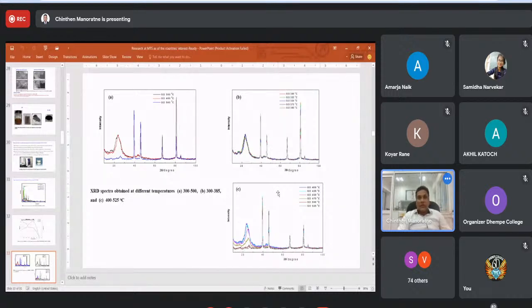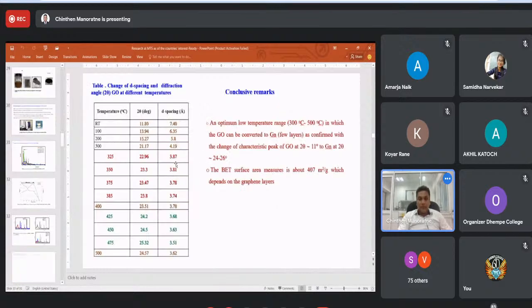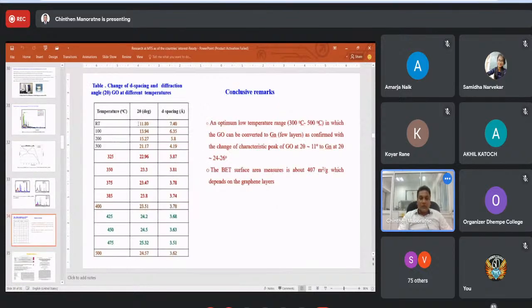Reduction of a certain amount of temperature is also economically useful, because that is more energy saving. And we found that 475 is the minimum temperature that is enough to convert this graphite oxide to graphene. And this corresponds to the theta change and d-spacing. You can see that at 475 you have the graphene structure. So this is one study we did at the materials technology section, and we have obtained a few layers of graphene with a surface area of about 400 square meters per gram.